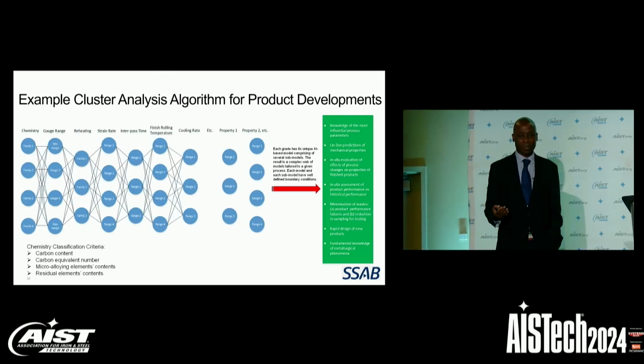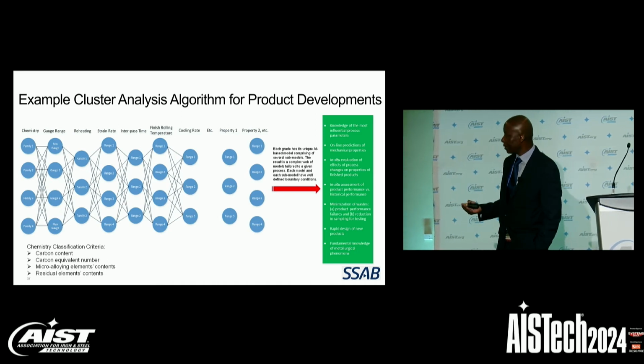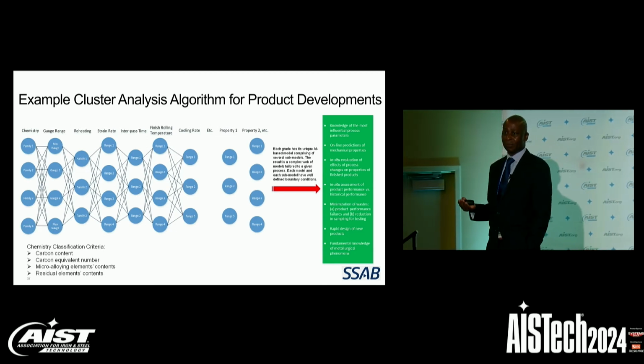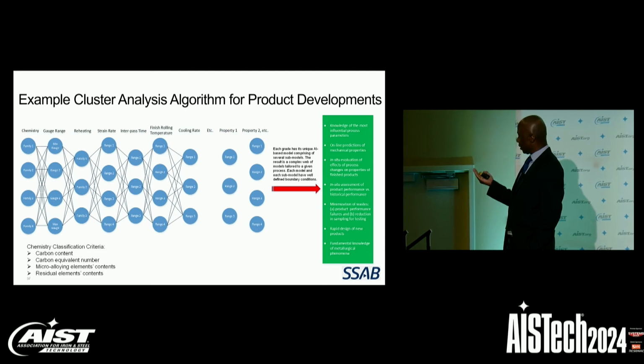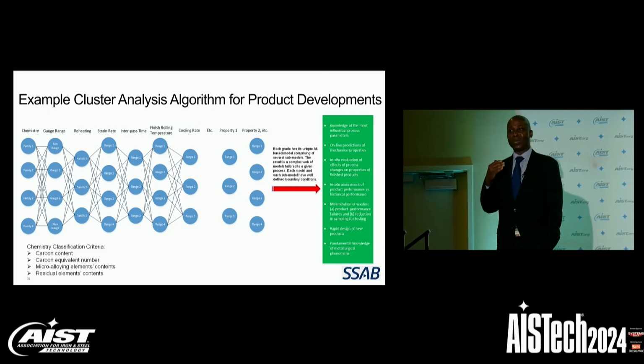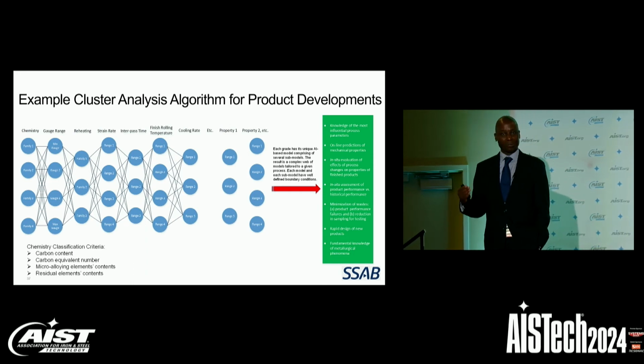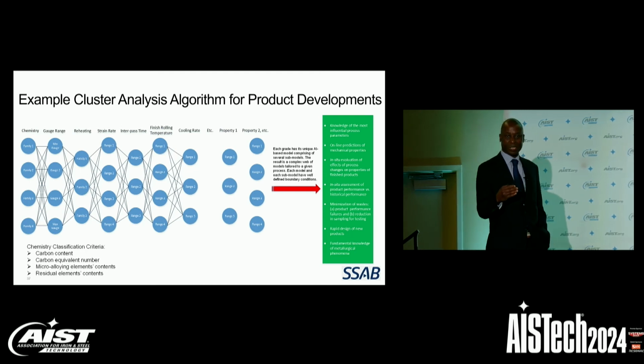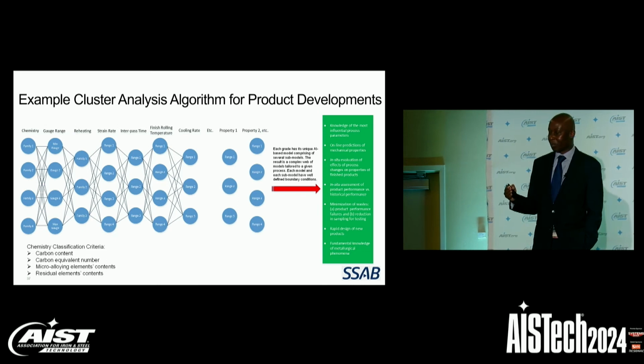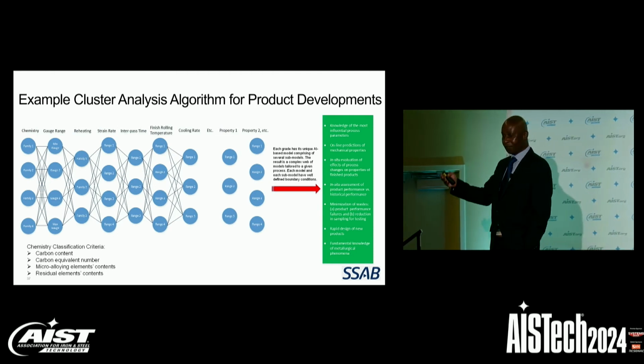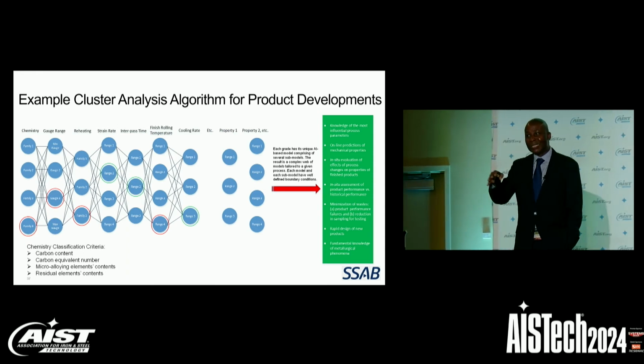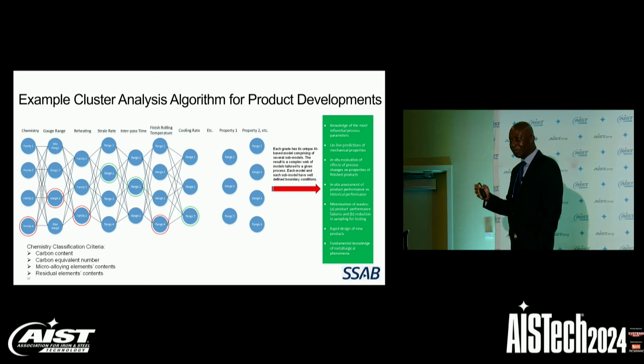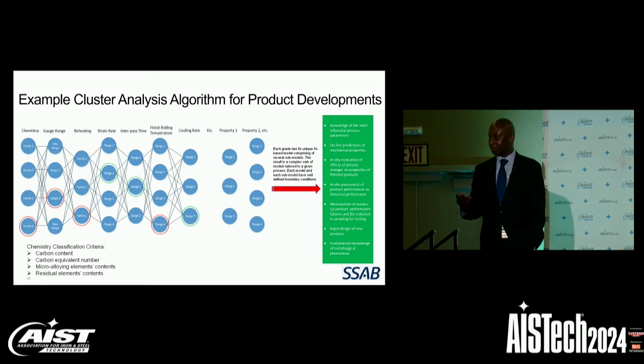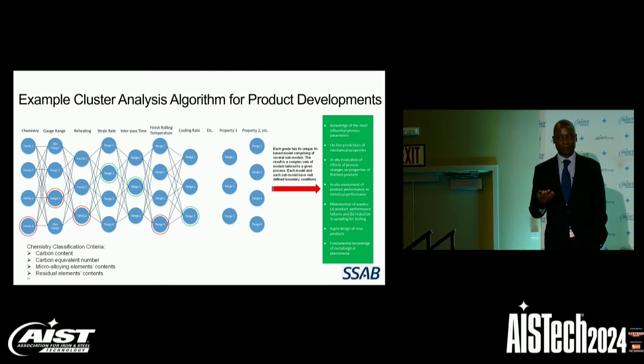So a potential solution to minimizing such waste with respect to product development is to maybe apply a cluster analysis algorithm for product development. For these particular kinds of cluster models, we can identify measurable and known process variables that impact microstructure and mechanical properties. And then based on historical data, classify each process variable into clusters with tight boundary conditions. Each grade, each chemistry type will have its own cluster model. This way, we can identify a combination of process variables that will lead to certain mechanical properties. Such a model can be applied online for troubleshooting and prediction of microstructure. It can be used offline for design of new products.